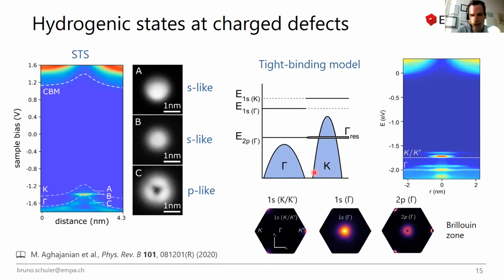And it turns out that these states do originate from different band maxima. It's also what you expect: you have this S- and P-like state that emerge from different band extrema, like at the K, K' and gamma point. So in collaboration with this theory modeling, we could assign where this wave function actually comes from, and why it appears and why it has such binding energies, which are quite significant again.